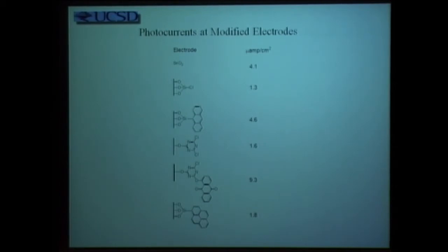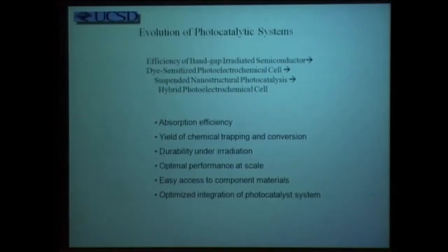Notice that with all of them, the modified electrodes showed electrical effects that are parallel to what I earlier described for titanium dioxide. So generation of currents at this modified electrode is the first way you can determine efficiency. It's important to think about how we would evolve photocatalytic systems. We started out with band gap irradiation, and we described that as a way of doing organic synthesis, of generating hydrogen, and as a means for cleaning up pollution.